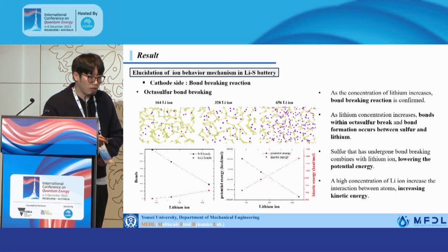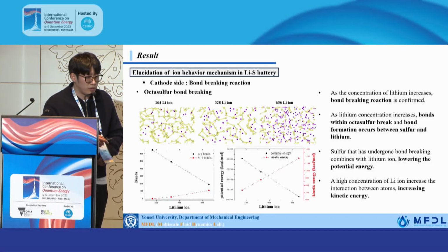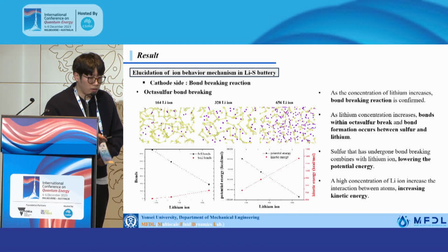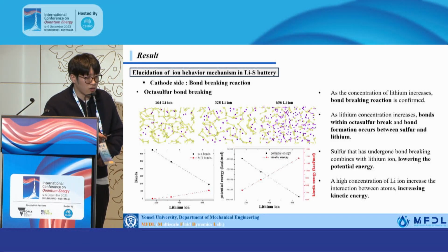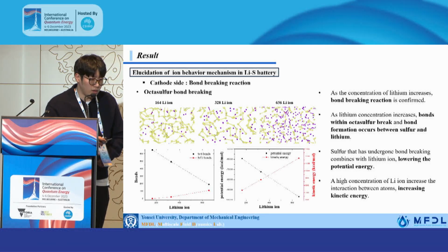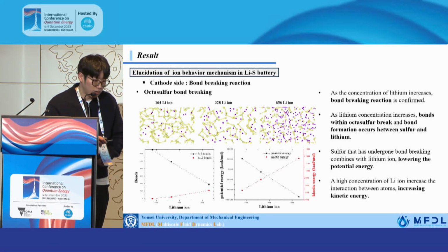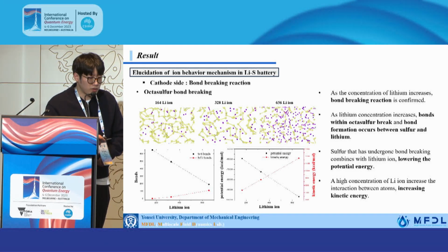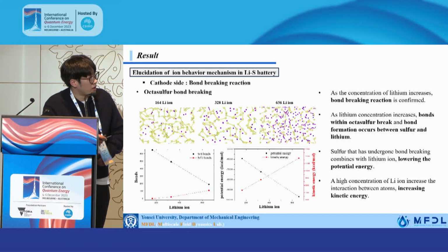And also we check the octasulfur bond breaking during the repeated charging and discharging cycle. And as the concentration of the lithium increases, the bond within the octasulfur breaks, and the bond formation occurs between the sulfur and lithium. And sulfur has undergone the bond breaking, so it can lower the potential energy, and the high concentration of lithium increases the interaction between the atoms, so it can increase the kinetic energy.